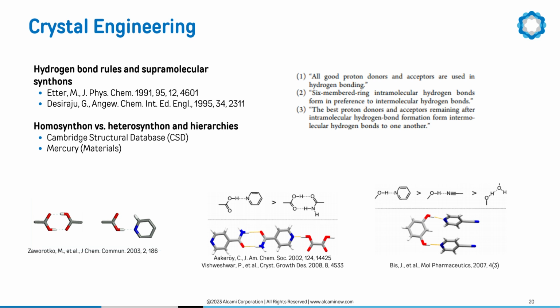Further studies on heterosynthons involve their formation in the presence of other competing functional groups. For instance, in systems where 3 moieties are present, carboxylic acid, pyridine, and primary amide, the carboxyl and the pyridine moiety consistently interact to form a heterosynthon, whereas the amide moieties consistently interact to form homosynthons. In another case, where structures were composed of phenyl, pyridine, and nitrile moieties, the phenyl pyridine heterosynthon reliably persisted in the co-crystal structures and took priority over the other possible synthons.